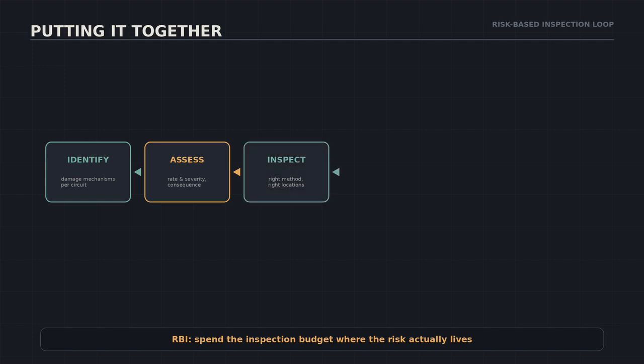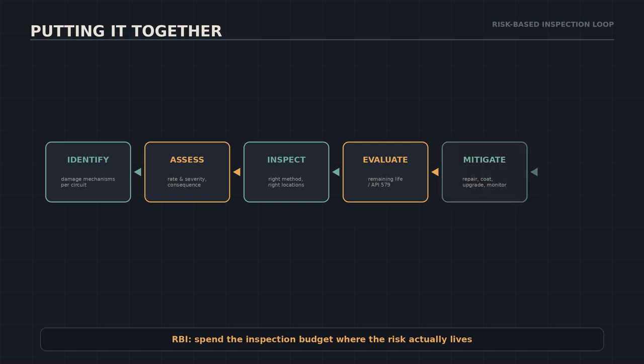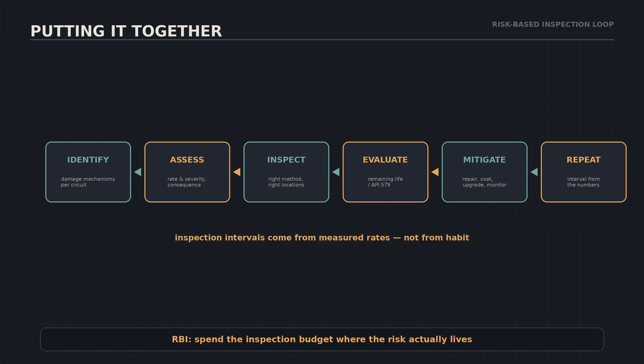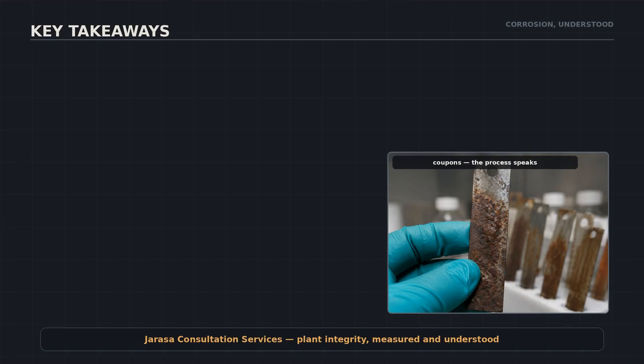Pull it all together and you get risk-based inspection. Identify which damage mechanisms are active in each circuit. Assess their rate and their consequence. Inspect with the right method at the right locations. Evaluate remaining life, fitness for service where needed. Mitigate: repair, coat, upgrade, or monitor. Then repeat, with the intervals set by the measured numbers, not by habit. That is how you spend the inspection budget where the risk actually lives.